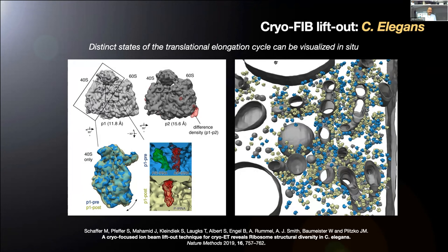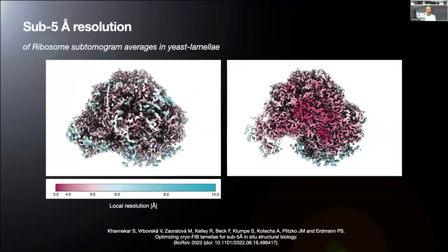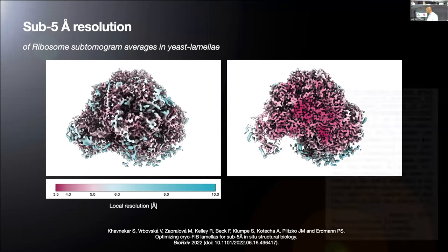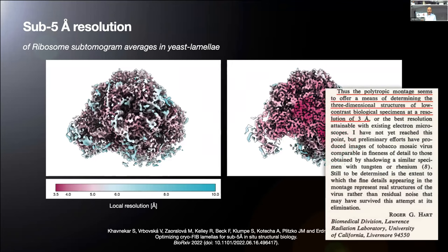Or when we go forward, we meanwhile have in yeast lamellae sub 5 angstrom resolution, which you can see here, which we have put out on bioRxiv already with a method development with platinum coated lamellae, where we increase the resolution and stabilize the sample. And we just revisit now what Roger Hart postulated, that we can reach this with tomography with the polytropic montage, 3 angstrom, we are almost there.